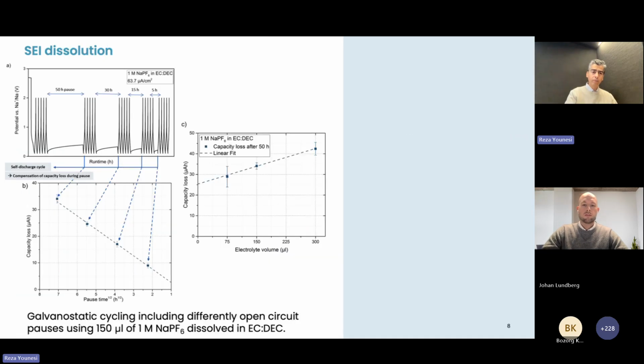So what we have found so far is that if you do this type of galvanostatic cycling and give different relaxation or pause time, as you see in the figure top left, then you can measure the capacity loss during this relaxation. And if you plot the capacity loss versus the square root of pause time, as you see in bottom left, then you can see that there is a linear relation between these two parameters, which indicates that this aging mechanism is a diffusion-based phenomenon, and it is kind of confirming that it is SEI dissolution, which is diffusion-based, leading to this capacity loss.